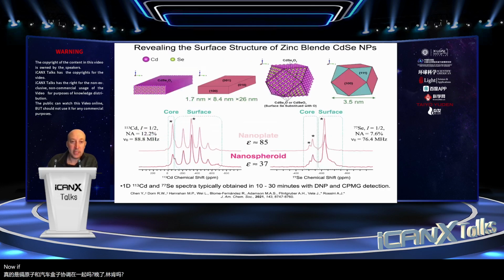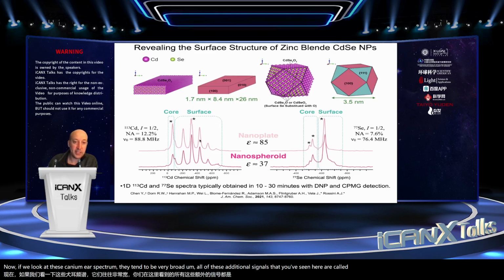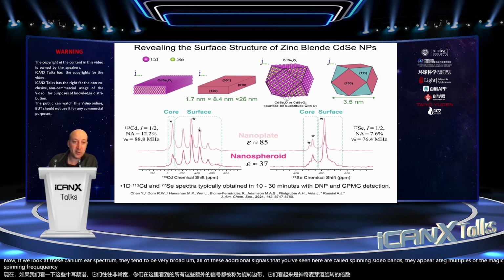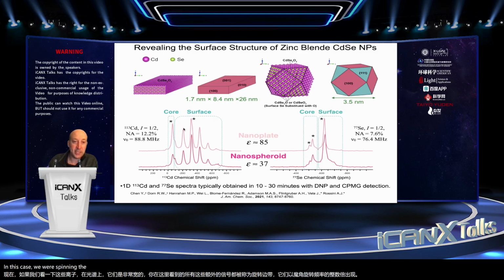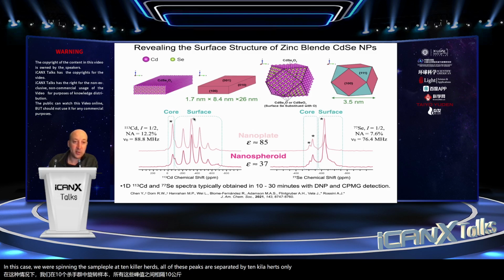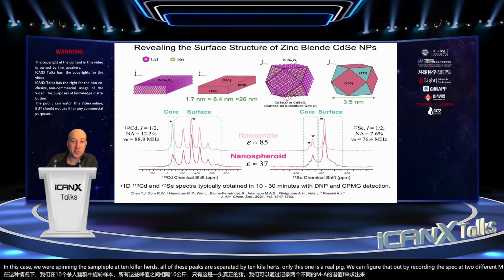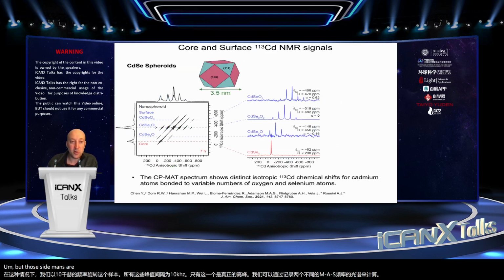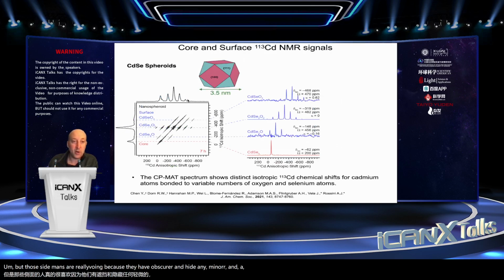Now, if we look at these cadmium NMR spectra, they tend to be very broad. All of these additional signals that you're seeing here are called spinning sidebands. They appear at integer multiples of the magic angle spinning frequency. So in this case, we were spinning the sample at 10 kilohertz. All of these peaks are separated by 10 kilohertz. Only this one is a real peak. We can figure that out by recording the spectra at 2 different MAS frequencies. But those sidebands are really annoying because they obscure and hide any minor NMR signals that might be there.